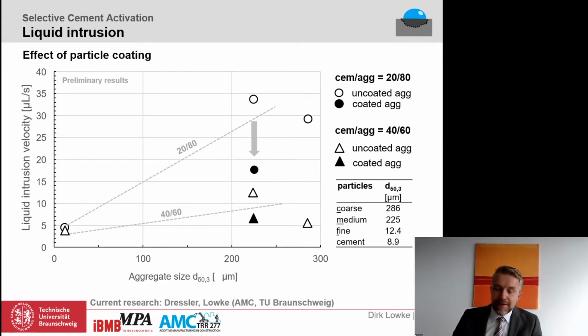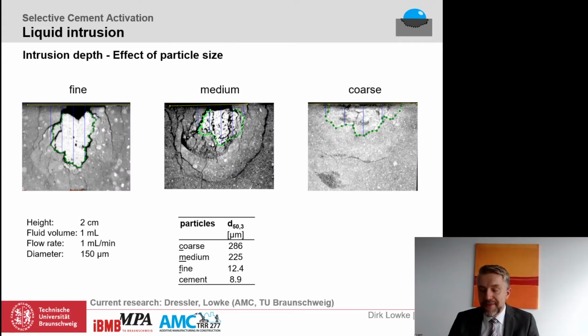The next important characteristic is the intrusion depth, since the complete penetration of the layer with the fluid phase is important to achieve a good layer bonding. To quantify this important characteristic, we used microtomography in this case. In these pictures, you can see the intrusion behavior in dependence on the particle size. On the left side, there are the finer aggregates, and on the right side, the coarser ones. And you can see a somewhat unexpected result, at least for us, that the intrusion depth is larger for fine particles than for the coarse particles.